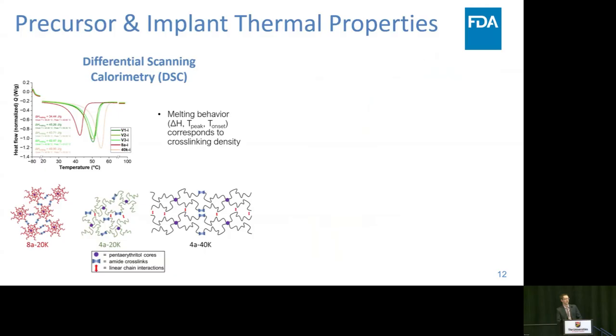Okay, so as I mentioned before, the API is in a crystalline form, and also in the aerogel state, the polymers tend to crystallize, and you have like linear chain interactions. And so we can measure this and look at product differences using the different polymer types using DSC. And the melting behavior that we observe here, with the heat of melting and the temperature, the peak temperature and onset temperature of melting, we can learn things about the cross-linking density and the crystallinity. And this has forward implications having to do with the swelling rates and the underlying microstructure. And so we can see subtle differences between the different vendors that we used, with the V3 polymer that has poorer functionalization, for example, having a more similar thermogram to the 40K polymer, whereas the other vendors are more similar to the 8-arm.